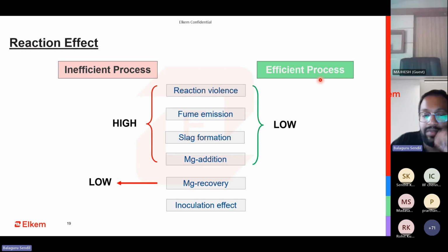We have a lot of formulas available. You take into consideration just the amount of magnesium you're adding, and then what is the residual Mg you are getting. We can go a step further and take into consideration your base sulfur, final sulfur, how much is your pouring temperature, how much is your tapping temperature, which gives you a much more realistic picture of what is your actual magnesium recovery. You need to target at least 60%, and you need to have good inoculating effect.